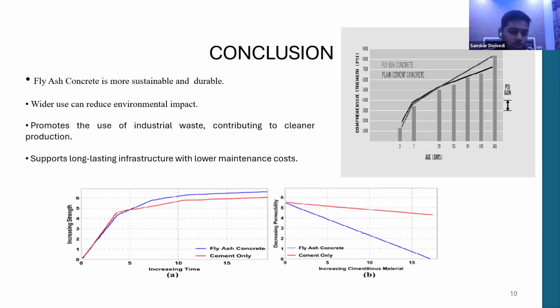So we come to the conclusion, and here are the points: fly ash concrete is more sustainable and durable. As you can see in this graph, the black one is plain cement concrete, and the gray one is fly ash concrete. After 56 days, we get higher strength for fly ash concrete, and at the last, 365 days, we get the highest final concrete strength.